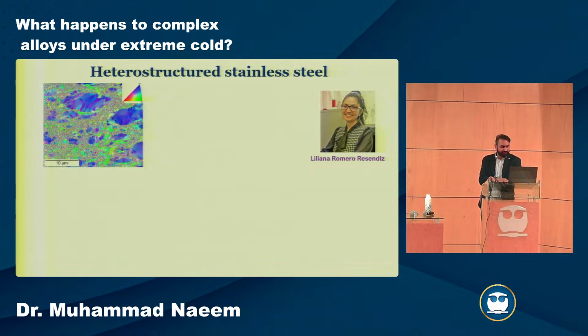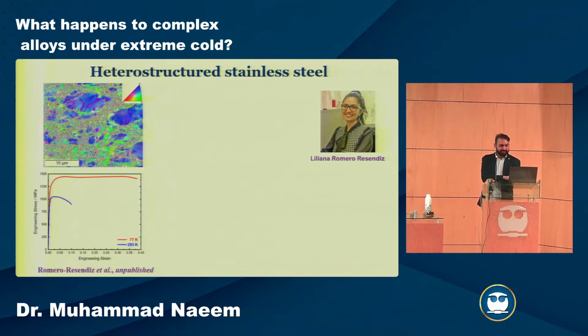Then we also worked on heterostructured stainless steel, which was with Dr. Liliana. In this case, we did experiments at room temperature and 77 Kelvin. I think you already know her, and you can talk to her about it. This is a heterostructure material, which has different sizes of grains, very fine and a bit coarser. And it has very interesting results. Because it was heterostructured, it had a very high yield strength, because usually with steel you have 200, 300 megapascal yield strength. Of course, you have to sacrifice something, but it still has a reasonable ductility. But when you go to low temperature, we have an increase in strength, but also look how much the ductility has increased. That's really amazing.